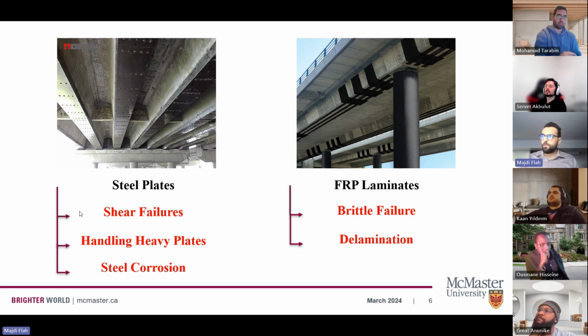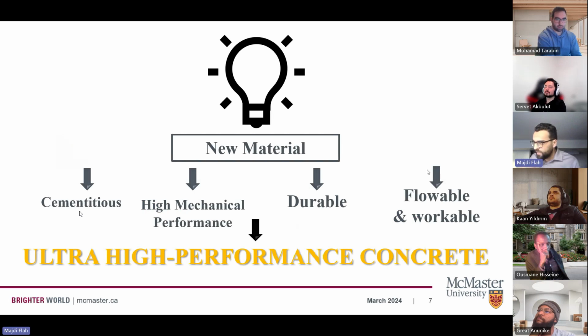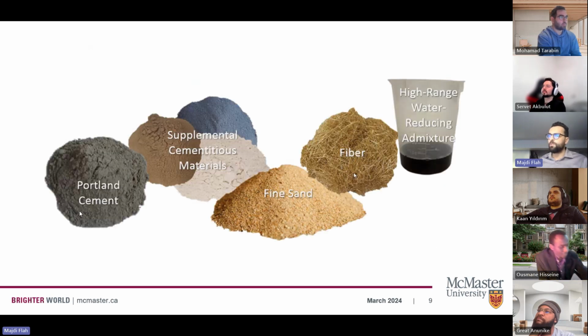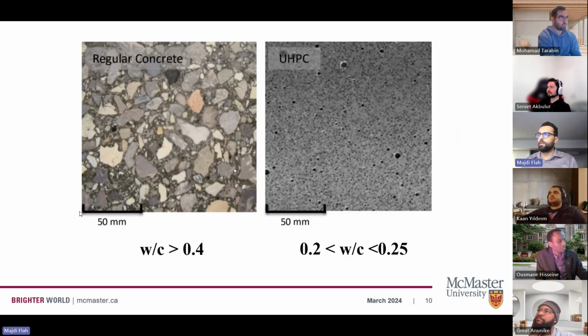which we are trying to avoid. So the idea now is to think of a new material which can be cementitious, highly performant, durable, and at the same time flowable and workable given the tight areas where we're going to do our repairs. So that's why now we are thinking of an ultra-high performance concrete. So the UHPC is made of cement, SCMs, fine sand, fibers, and high-range water reducers. And the secret behind the formulation of the UHPC is the low water cement ratio.